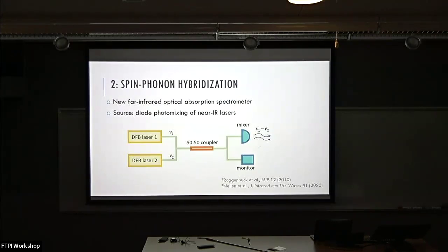Okay, so moving on to the second part, which is the spin phonon thing. So to look at these phonons, as I mentioned, the energies are very low. So the lower mode is around 1 meV, which is 250 gigahertz in frequency units. This is very low. So it falls in this dreaded terahertz gap, which nowadays what people do is they use pulsed techniques. So you can go to these frequencies, but the bigger issue is that the samples are bulk. So these are not thin films, and they have very high conductivity. So there's no way you can do a transmission type experiment. And the reflection coefficient is basically 1.